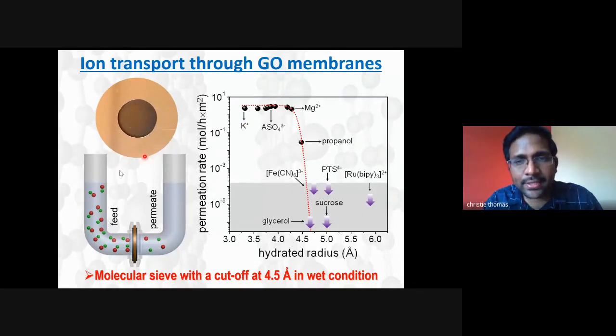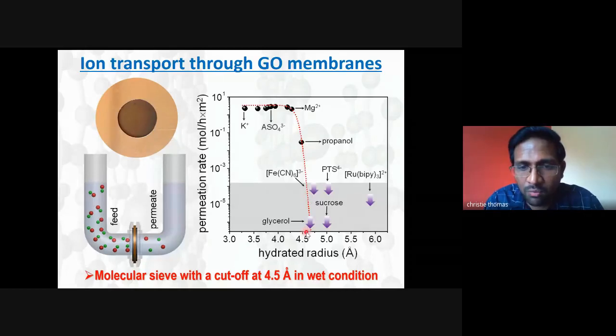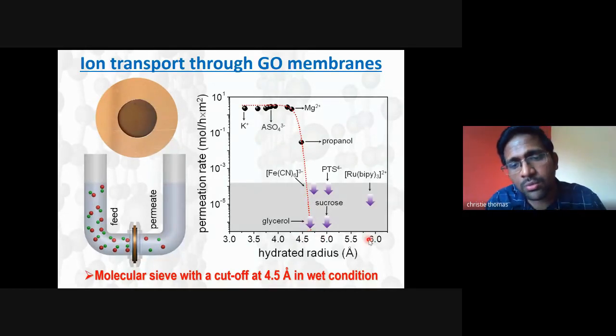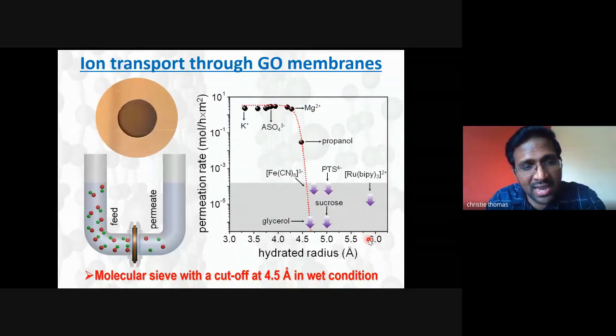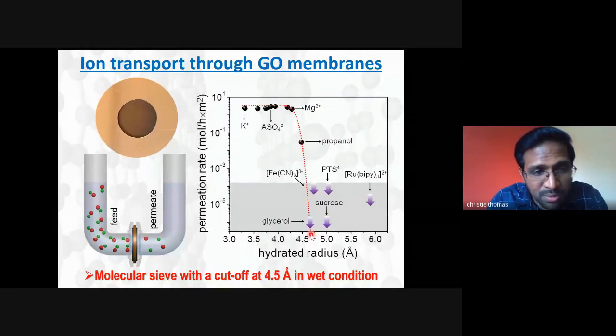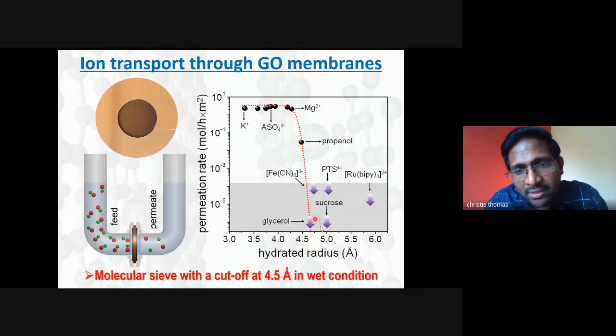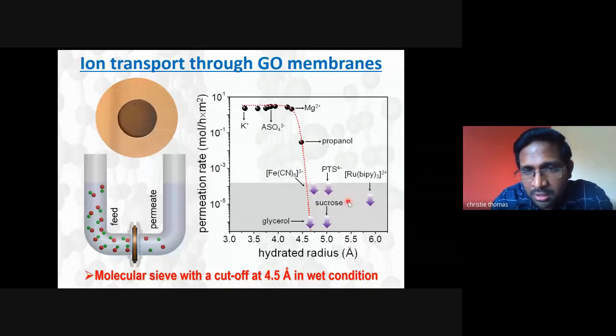You can see that the permeation rate drastically goes down when the hydrated radius of the ion goes beyond 4.5 angstrom. When the hydrated radius goes beyond 4.5 angstrom, the permeation drastically goes down and falls below the detection limit.